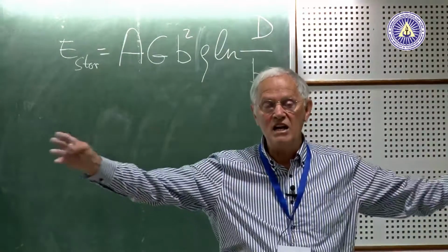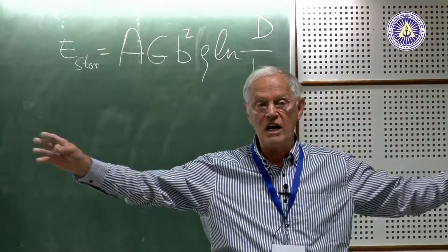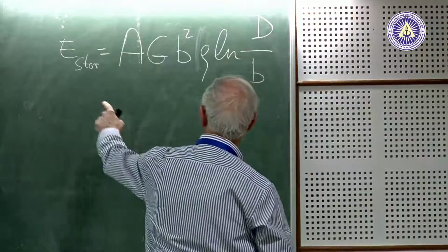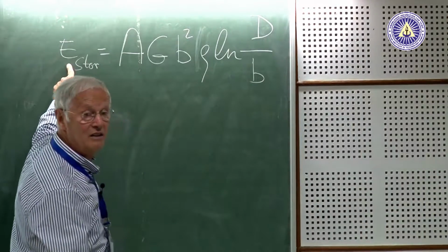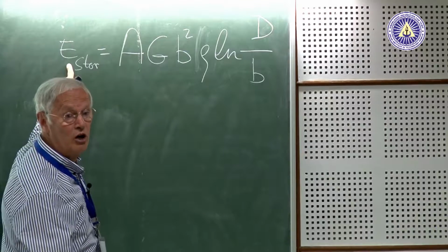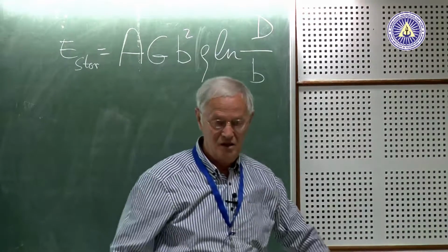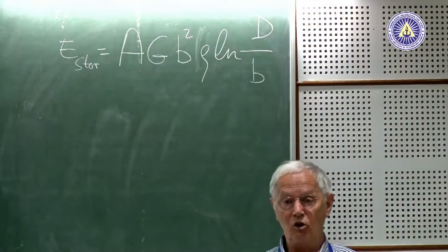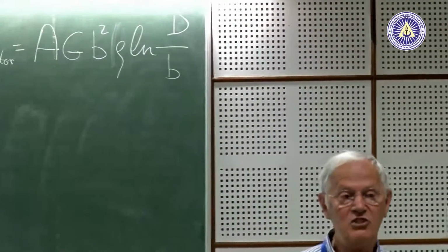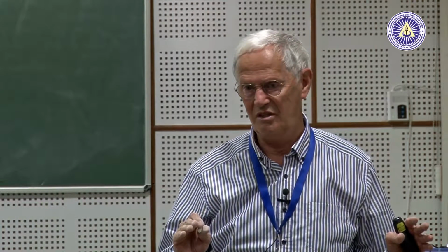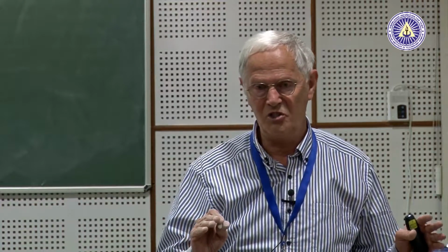Now what about the size of your crystal? If you increase the size of the crystal, the elastic stored energy is again logarithmically singular, although the dislocation density is a constant. Now how was this problem solved? Independent of line profile analysis, just in mechanics, in dislocation theory. How was this solved? By introducing the effective outer cutoff radius.